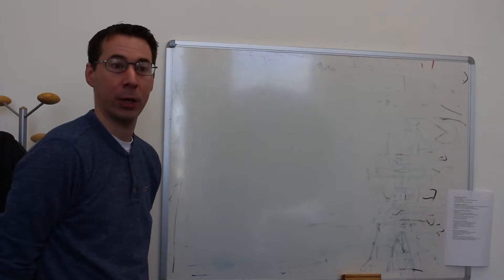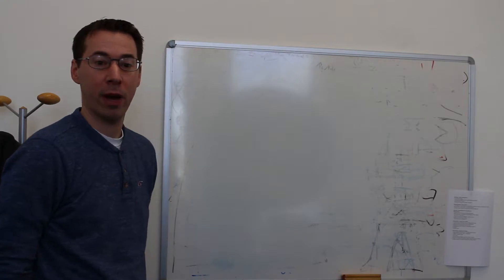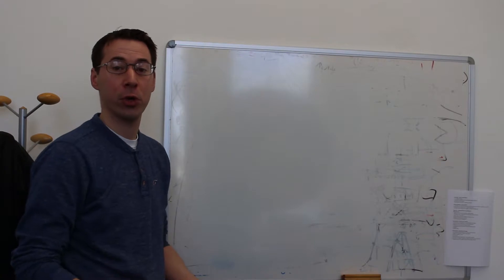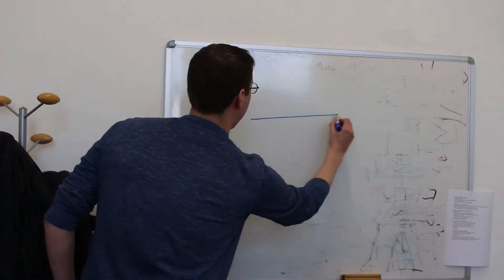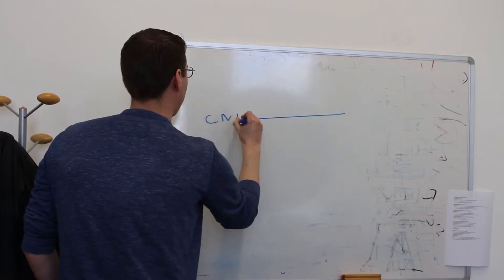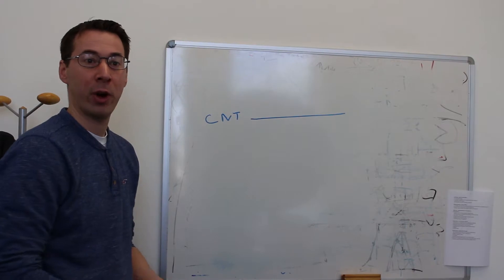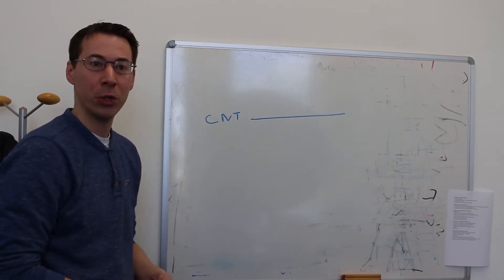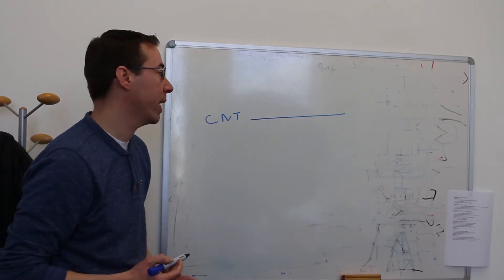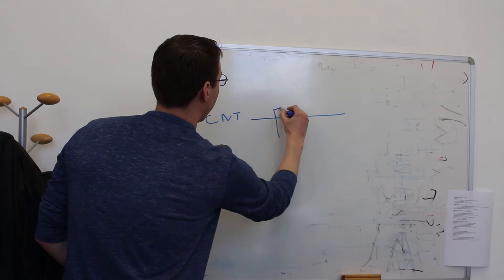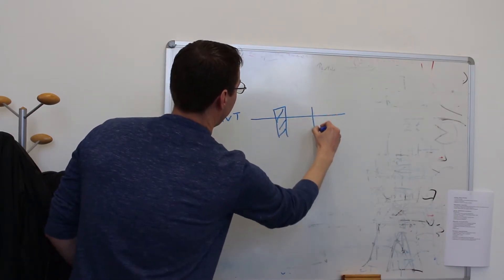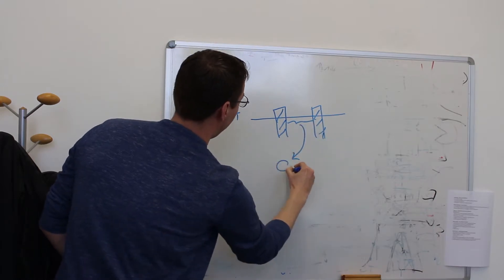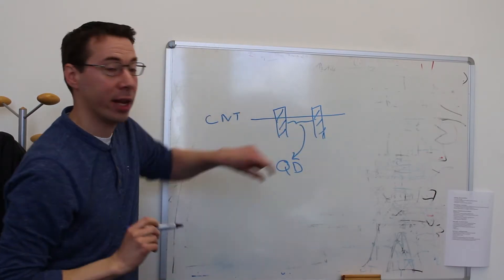So how do we make our qubits? The qubits are defined in carbon nanotubes, and the carbon nanotubes are grown in a furnace on a substrate. So let's say this is my carbon nanotube. And we locate these carbon nanotubes using an atomic force microscope. And then we go into our LCN clean room to define quantum dots within this nanotube using electron beam lithography and metal evaporation. So for example, we define two electrodes here, so that we can define a quantum dot in this section here in the middle.